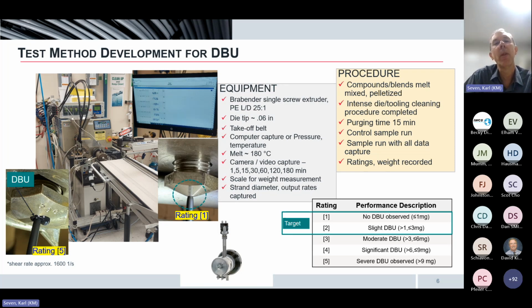But the other thing I want to point out here is that we did take precautions to adequately clean the extruder and all the tooling associated with that between samples, so as to remove buildup. A lot of these processing aids do build up on the tooling, and that can remain on the tooling even after that processing aid is no longer present. And so precautions were taken with regard to that.